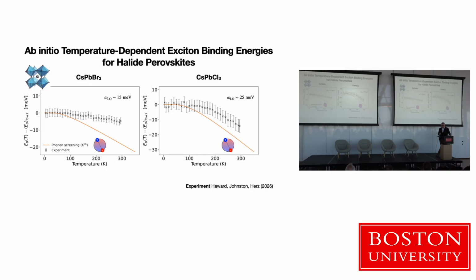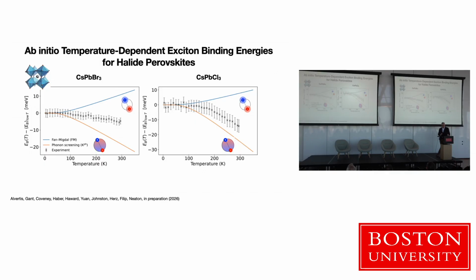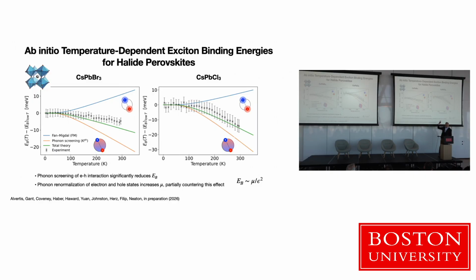And what we can do is look at the different components of how phonons change the exciton. The screening, which is in orange, and the renormalization of the individual electrons and holes that the exciton is composed of, that's in blue. And really those two effects in combination are what give rise to the experimental trend. And what is very interesting and important is that the screening part is really the dominant trend.